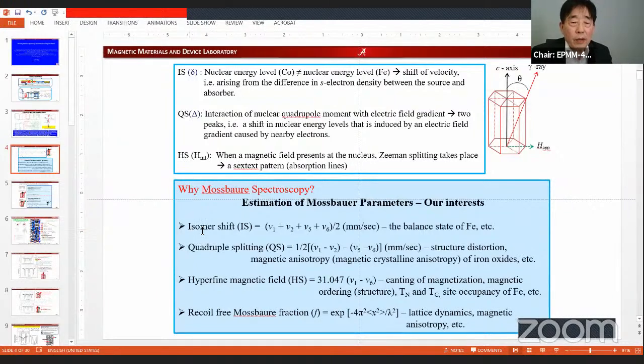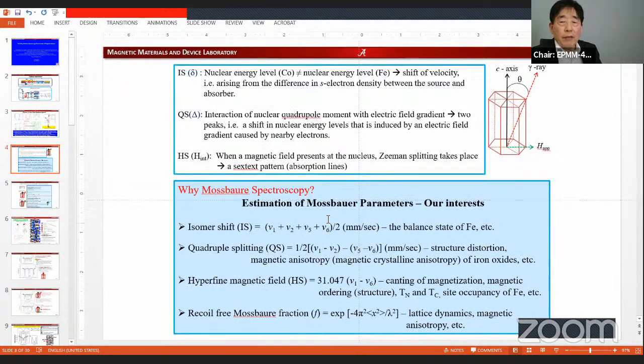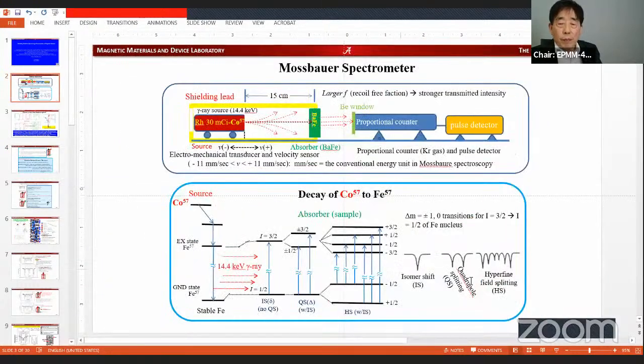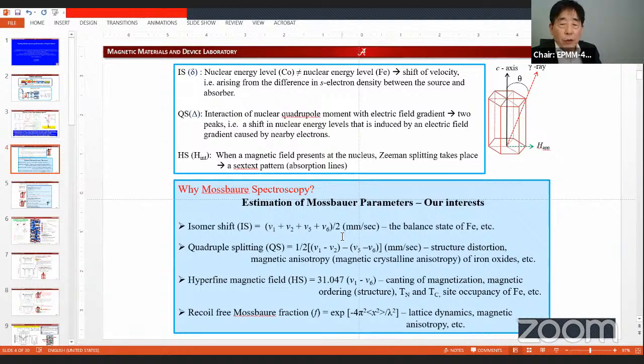Therefore, we can calculate the isomer shift as follows: identify peaks v1, v2, v3, v4, v5, v6. Once you detect that number, divided by 2, that gives us the isomer shift. And once the isomer shift number is obtained, we can understand the valence state of the ion in your compound.